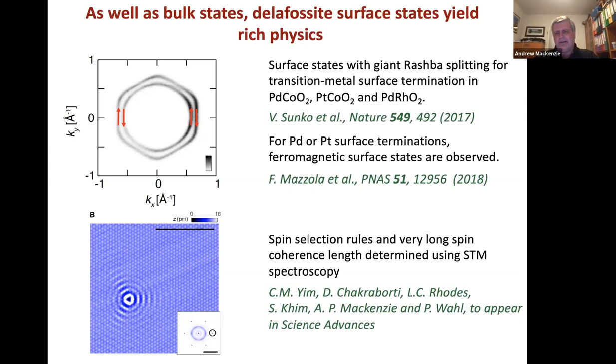Well, if I could, then maybe the second question would be, I'm interested in studying the evolution of the surface texture of surface faceting. So that itself, that cleaving doesn't lead to a final state. There's an evolving texture generally. Yeah, but what I'm thinking is that the bonds are pretty strong, and so these are relatively high melting point materials. So the actual mobility of structures on the surface at room temperature, the kinetic barrier is huge. These ones are essentially static.